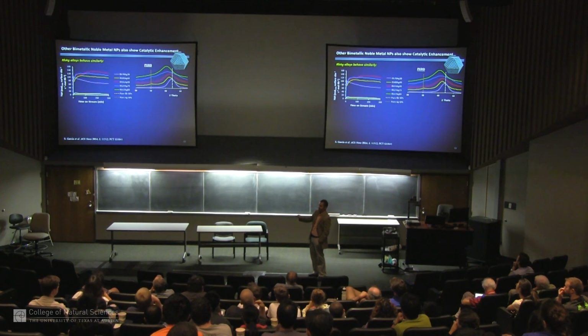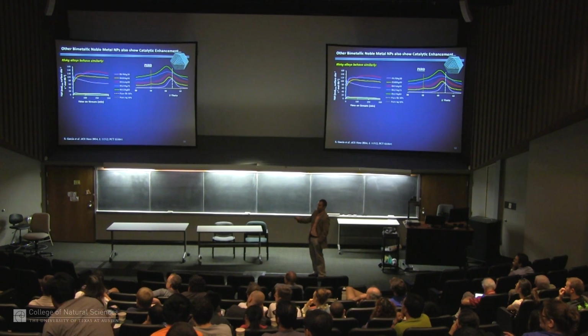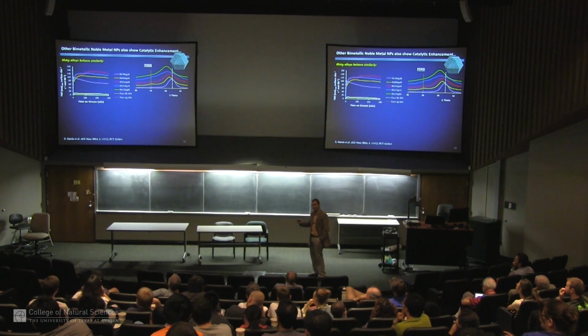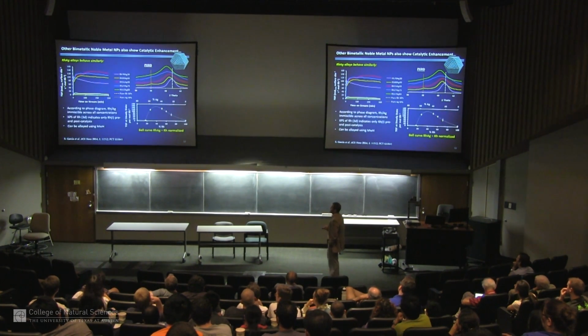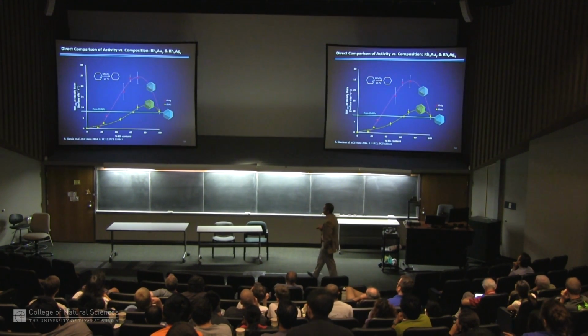And he probably looked at me to start with and thought, well, you've got rhodium here, you've got silver here, aren't you just making synthetic palladium in the middle by alloying one-to-one? And so we ran some palladium particles, and sure enough, the palladium particles are kind of down here. So something really was going on with these alloys. Again, here's the bell curve that shows you could be around 50%. I'm going to put these two together.